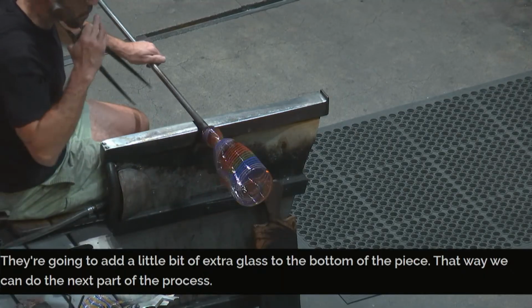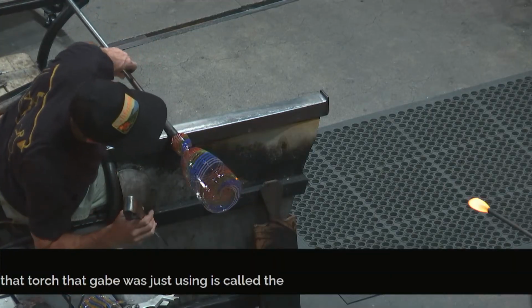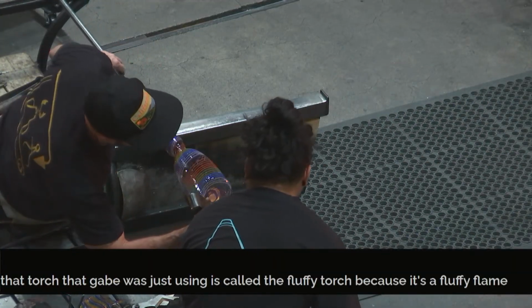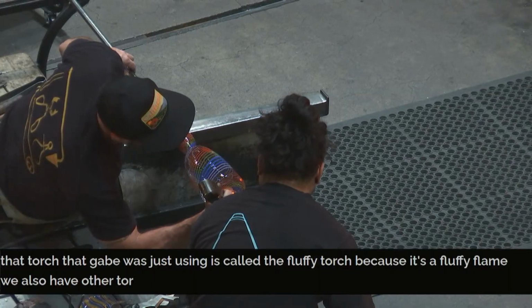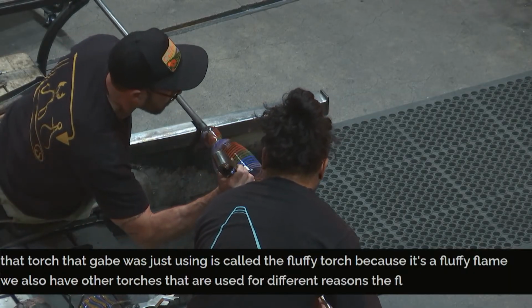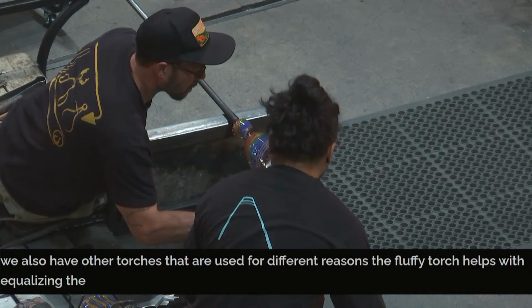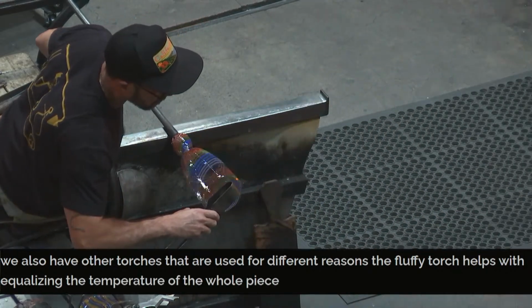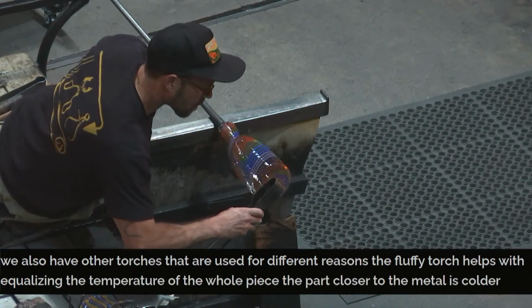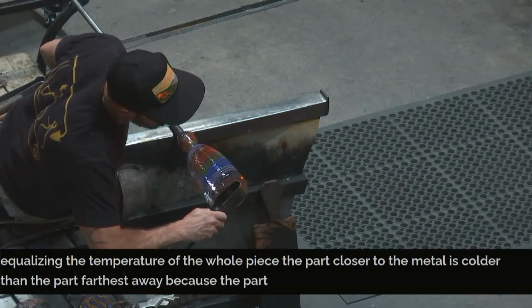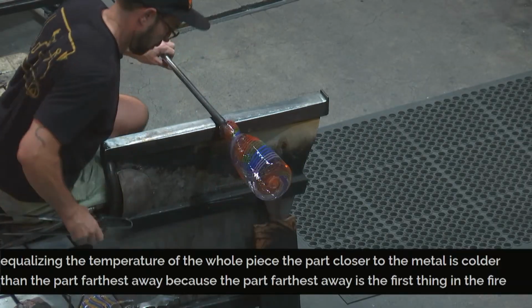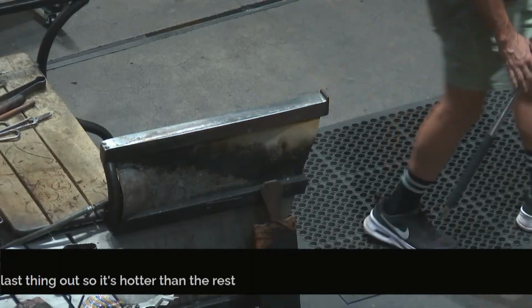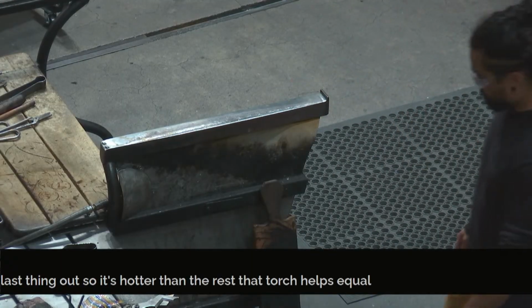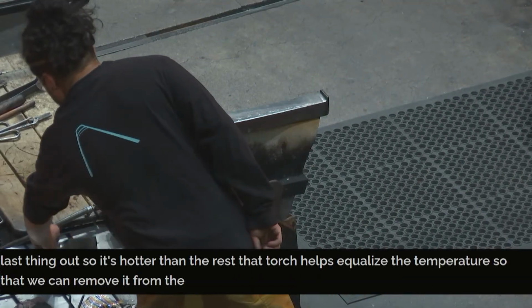That torch that Gabe was just using is called the fluffy torch because it's a fluffy flame. We also have other torches that are used for different reasons. The fluffy torch helps with equalizing the temperature of the whole piece. The part closer to the metal is colder than the part farthest away because the part farthest away is the first thing in the fire and the last thing out. So it's hotter than the rest. That torch helps equalize the temperature so that we can remove it from the blowpipe without sending a crack down the side of it.